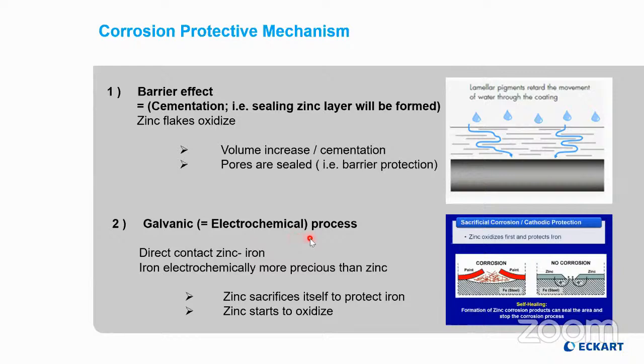Also, a galvanic effect is of importance when using zinc flakes. With a direct zinc to iron contact, through the flow of electrons, the zinc works as a sacrificial electrode, and instead of steel, the zinc pigments oxidize. In the oxidation process, they form zinc oxide. In addition to this, the zinc oxide generates an additional barrier protection. So you have a galvanic process and a double barrier layer: the initial flake layer, and the barrier formation through the zinc oxide formation. Any pores and holes in the paint film are sealed by that zinc oxide.